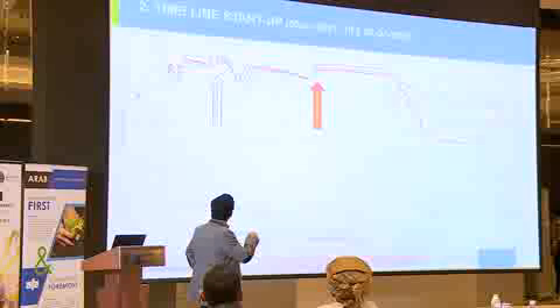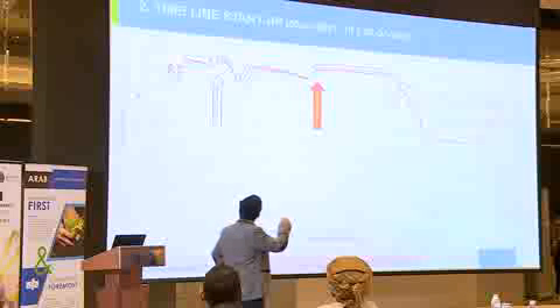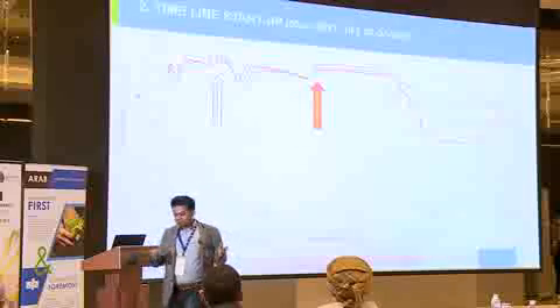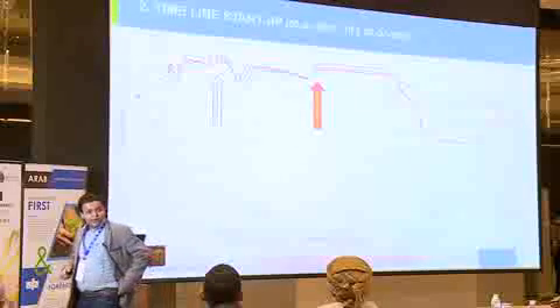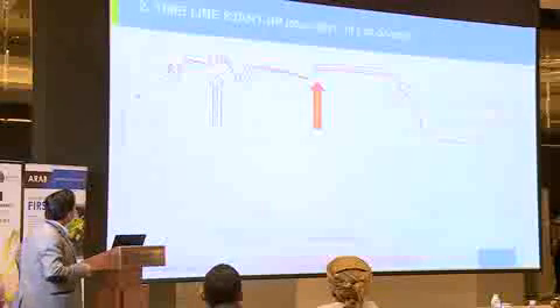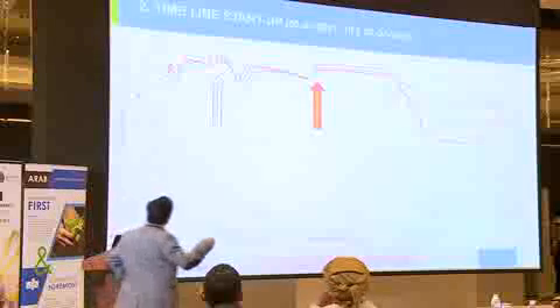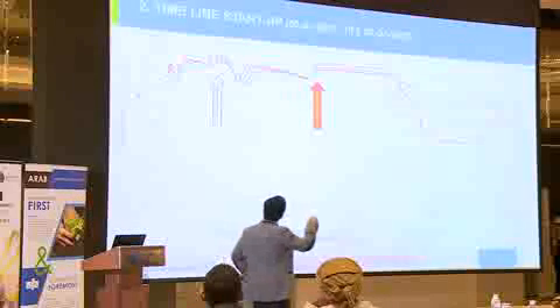So nobody cared about it. The temperatures increased, stabilized at conditions much higher than what you have normally. So this is something like 174 degrees C, 90 bar conditions in synthesis. They restarted the plant. So that's the second run.